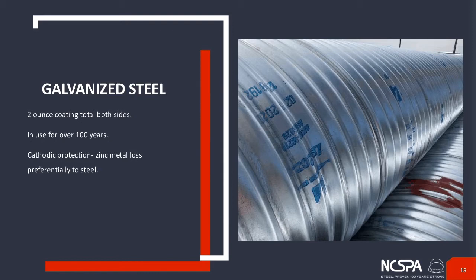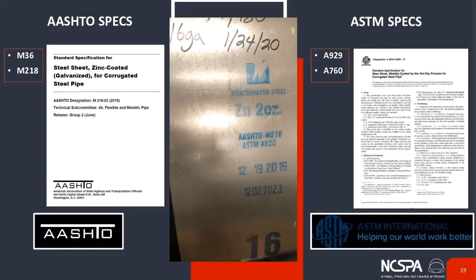You can see a sample of the corrugated metal pipe there with a stencil on it, and as you look down the pipe, you can see that stencil is repeated every few feet. So specifications for galvanized steel pipe, we have AASHTO specs, of course, and then married up with ASTM specs on this slide. AASHTO M218 is the specification for the coil material, and M36 is the specification for the product itself. Flipping over to ASTM, same thing. You can see the related equal specs to the AASHTO specs there, A929 and A760. And then again, you can see on this galvanized coil in the middle the stencil that has all the pertinent information on it: the manufacturer, it's zinc 2-ounce coated, AASHTO and the ASTM spec, date it was manufactured, the heat number, and then the 16 at the bottom tells you it's 16 gauge.